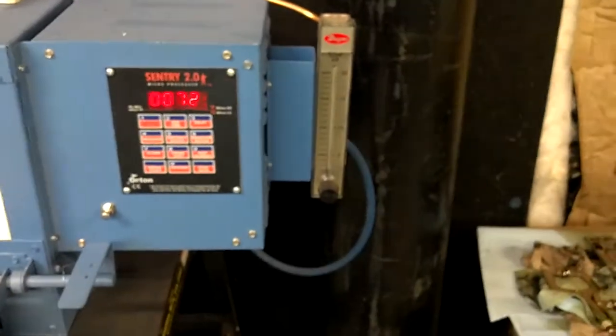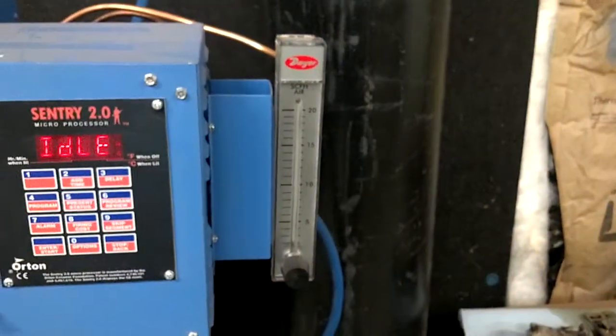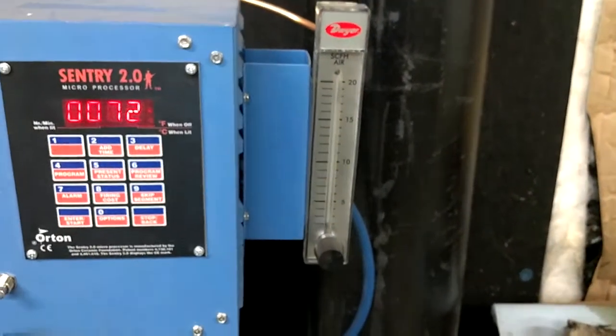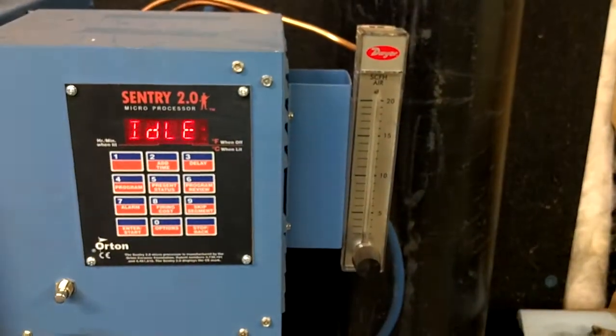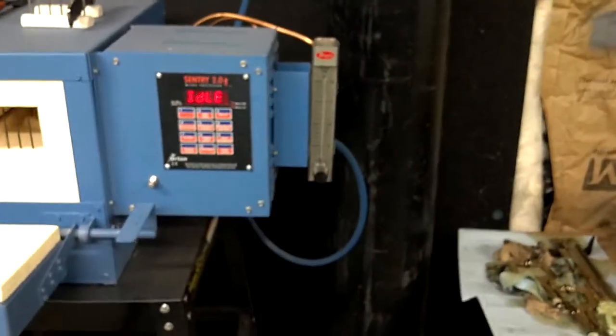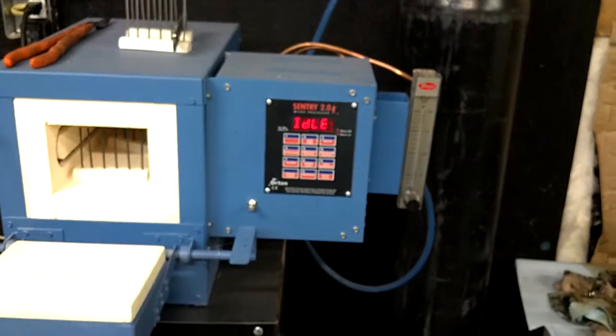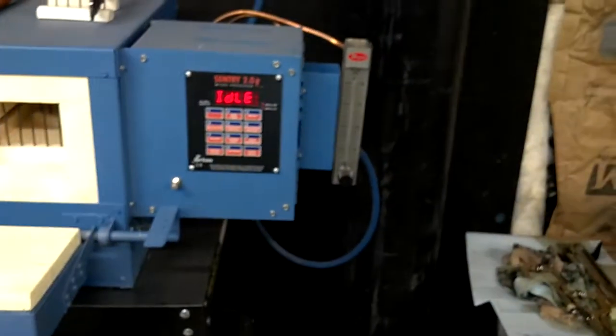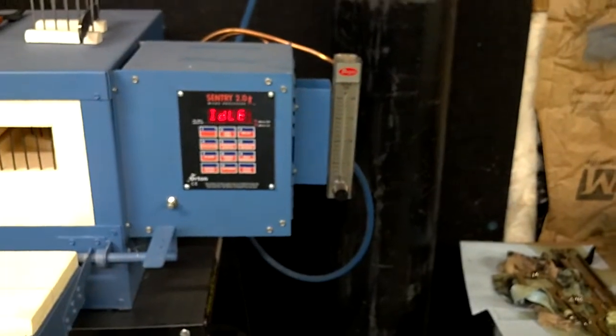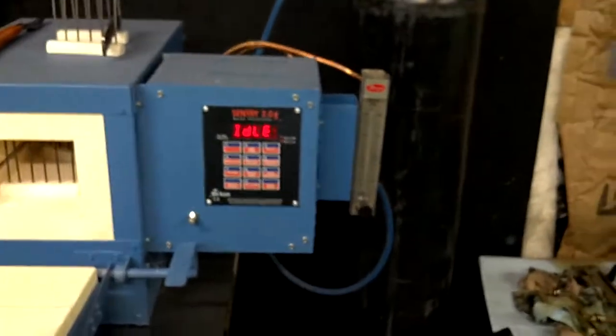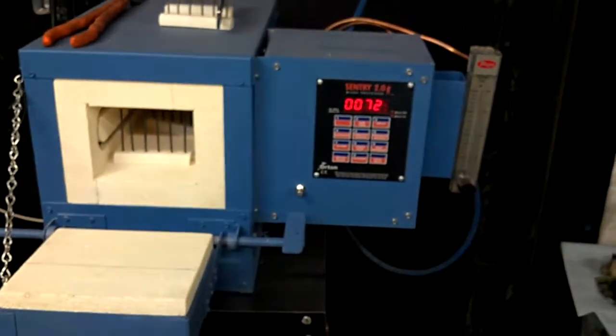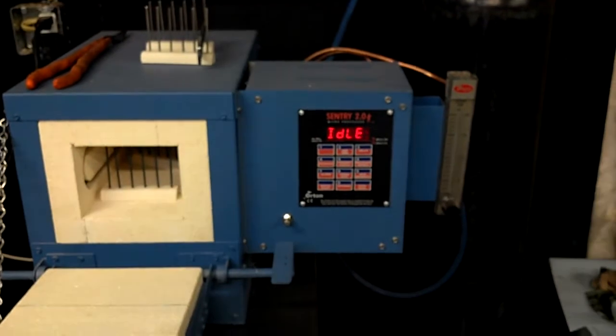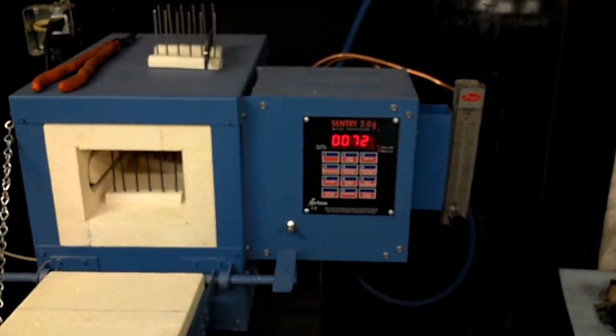We did a little testing on some 440C and we set our flow meter at about seven and we didn't have good luck with that at all. There are no directions that tell you, for those of you interested in buying one of these ovens with flow meters, there are no directions that tell you exactly what to have it set on. You just want to get yourself positive pressure, you want more gas flowing out of that box than oxygen flowing in.